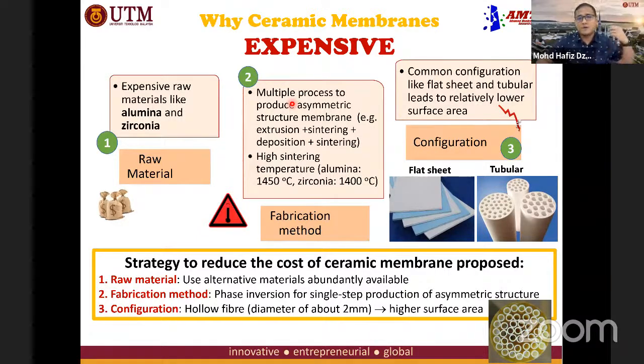So we have to do the extrusion, sintering, deposition, sintering, and followed by a few more steps in order to get the desired structure. And also the high temperature sintering for the commercial material like alumina and zirconia. Okay, so that makes the process to produce the ceramic membrane energy consuming. And also the configuration for the current ceramic membrane. Normally you can find either a flat sheet or tubular, they're commercially available. And these types of configuration lead to a relatively lower surface area.